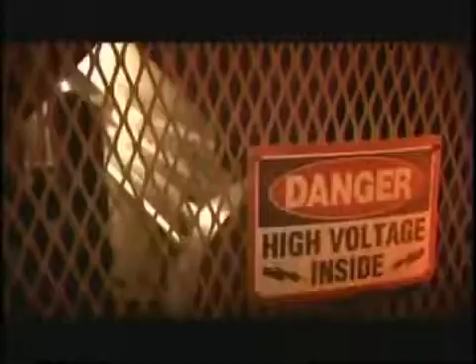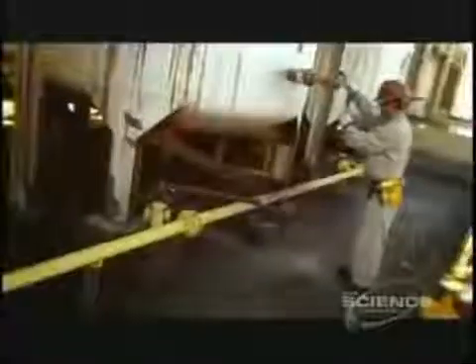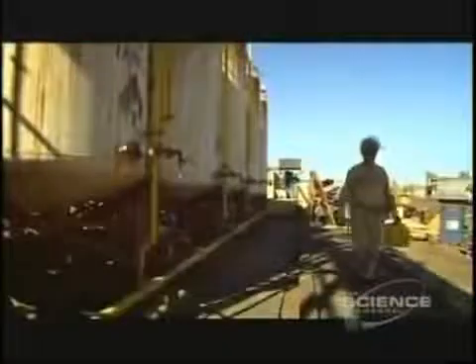To be turned into a metal suitable for aerospace applications, it now needs to undergo a complex and expensive refining method called the Kroll process. Here at Henderson in Nevada, specialist firm Timet produce 22,000 tons of titanium products every year. The process begins by first turning the titanium ore into a gas. That's done by heating the ore to 1,800 degrees Fahrenheit and adding chlorine gas to form titanium tetrachloride, known to the scientists as TiCl4. As it cools, the tetrachloride is collected as a liquid.